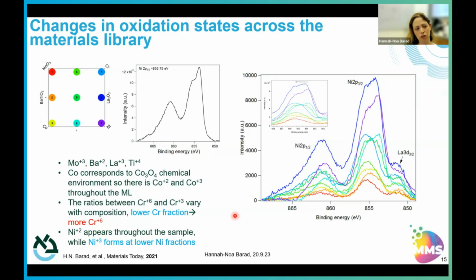And what we attribute this to is the fact that these elements are situated within so many other elements, and they're all sitting in different levels of oxidation and reduction, if you can think of the oxidation reduction scales that we know for electrochemistry. And what we believe is that this actually helps to stabilize these different oxidation states, which would lead to really interesting activities, hopefully.